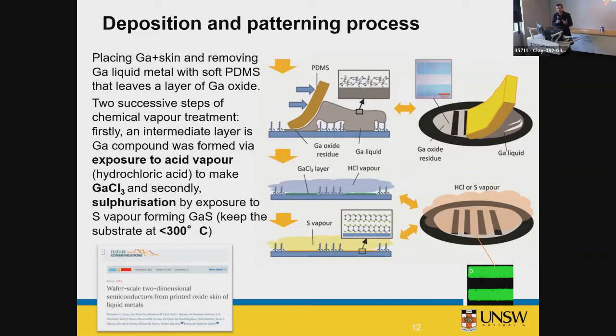Gallium oxide itself is a wide band gap semiconductor. You can use it for making transistors, for power electronics, or you can reduce the band gap here. For instance, in a two-step process, we expose it to sulfur, and we make two-layer gallium sulfide, which has a much lower band gap, and make devices. But as you see, the photoluminescence of these stripes, even doing everything by hand, is very homogeneously distributed. As you see, everywhere green and black. This was done by hand.